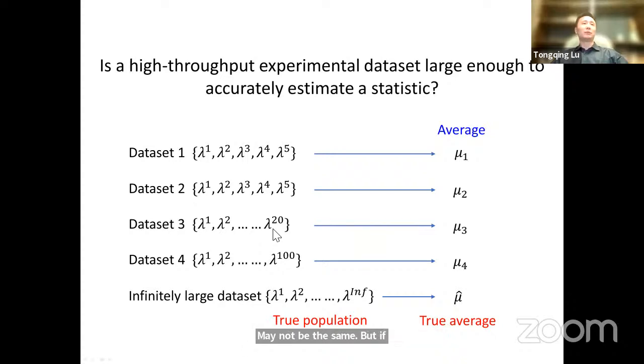But if we increase the number of tested specimens, we get another average, for 20 or 100. Imagine in a hypothetical experiment, if we can test an infinitely large number of specimens, we get what is called the true population, and we can get a true average. Okay. So the question is, how different are these values? How different between mu1 and mu2? How different between mu1 and mu4 and the true average, right? So now we have a large data set, maybe 100 or 1,000, but is 100 data large enough to accurately estimate a statistic to approach the true statistic? Of course, average is just one statistic. Other statistics include, for example, standard deviation and quantiles and so on.